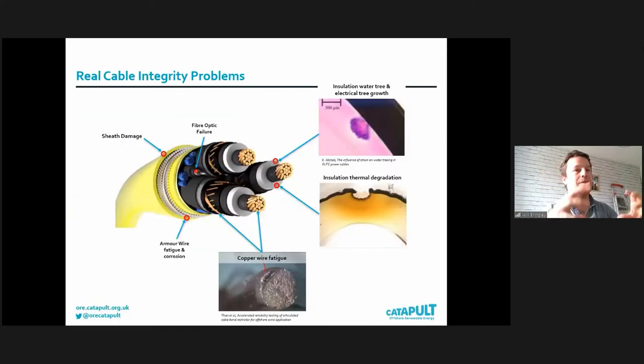So going from out to in on the component, we've got the outer sheath. You're in a floating environment, so the cable's going up and down on the seabed, and that can, over many years, abrade the sheath and then cause failure. And certainly in oil and gas, we've seen issues with sheath damage from fishing, but also how the sheath interfaces with the vessel as well. And then going into the cable, when you cycle a component, the thing that really suffers is the metallic components through fatigue cracking. The component that sees the largest level of strain, because it's on the outside, is the armor wire. So steel, particularly if it's not well corrosion protected, could be at risk from fatigue cracking.